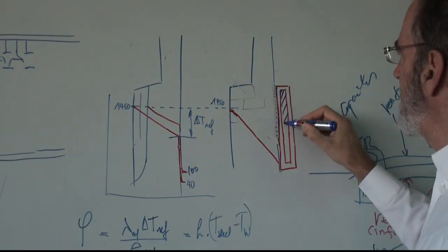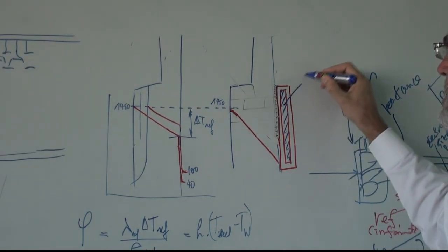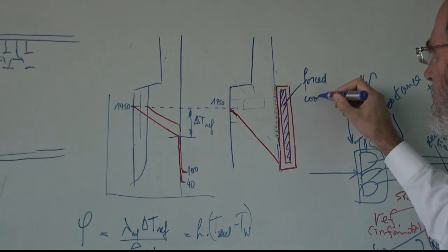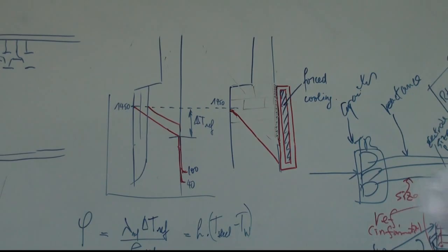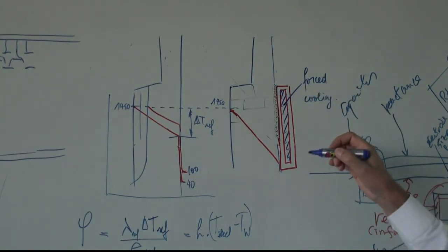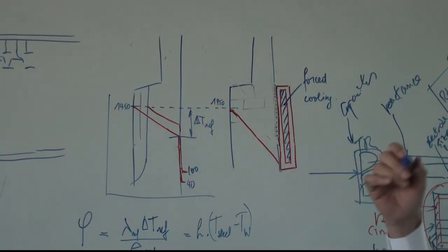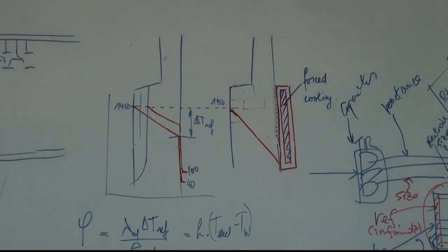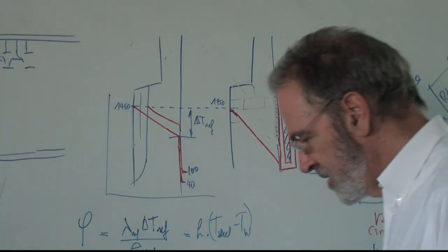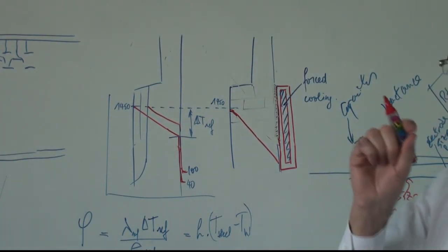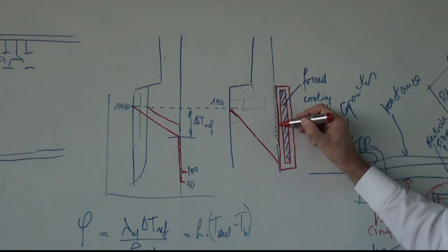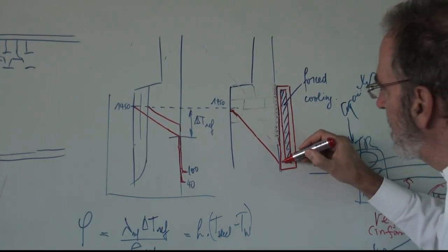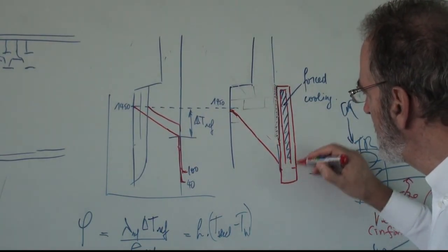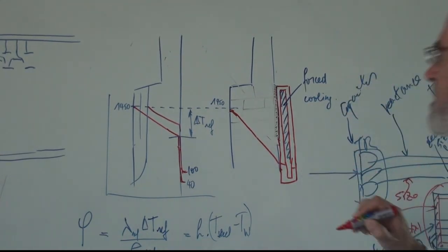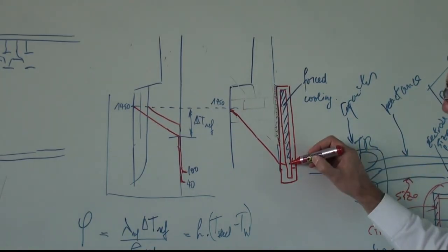since you are using inside the copper, this is forced cooling. Forced cooling means very high cooling coefficient, and it means the copper is at the same temperature as the water, and since copper is very conductive to heat, inside the copper there is also no or very small temperature difference, meaning this side of the copper is at the same temperature as the water. The gradient in the copper is like this, and this is the water temperature.